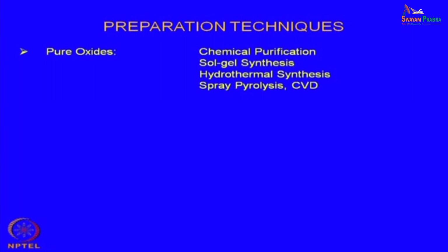So, therefore, starting materials need to be fine, and most of the time the particles will be finer than 1 micron size, and these days we are talking about nano size particles as well. So, sol gel is one technique by which you can make either micron size or nano size particles of different oxides or mixed oxides. We will come to that also. Hydrothermal synthesis is another area. It is not just sol gel, but you take a solution and then heat as well as pressurize. So, it is a combination of heating and pressurization.